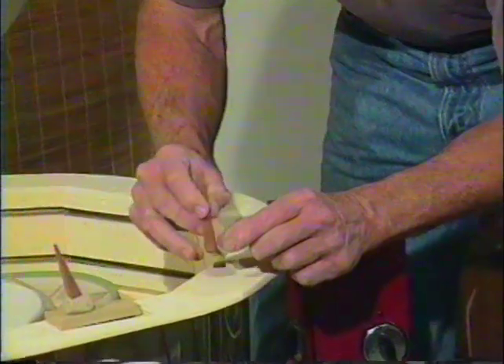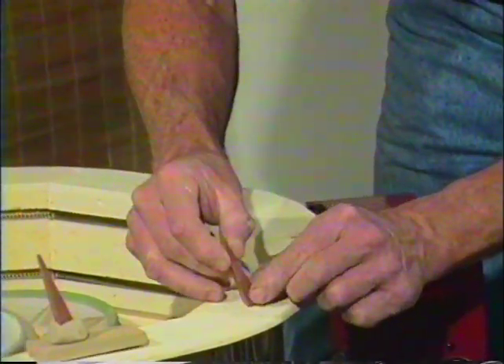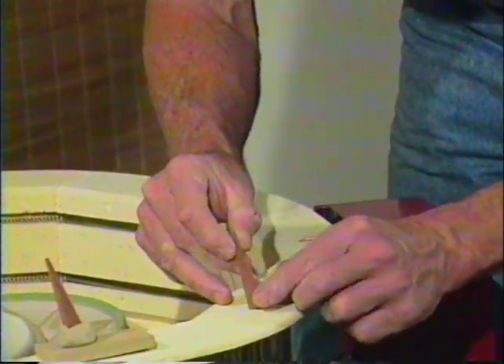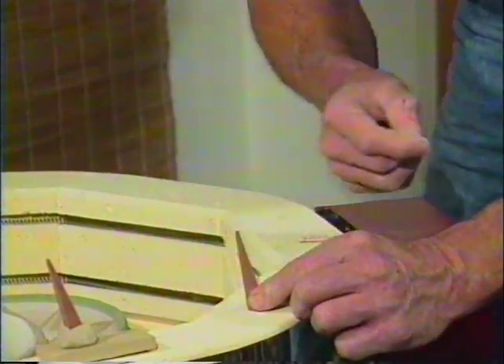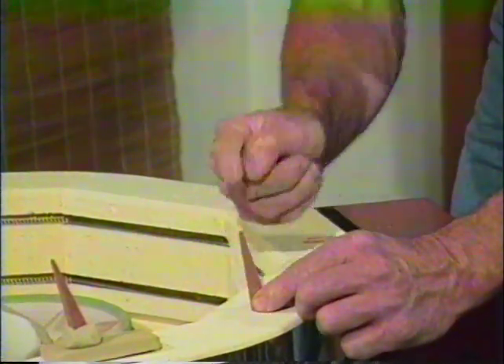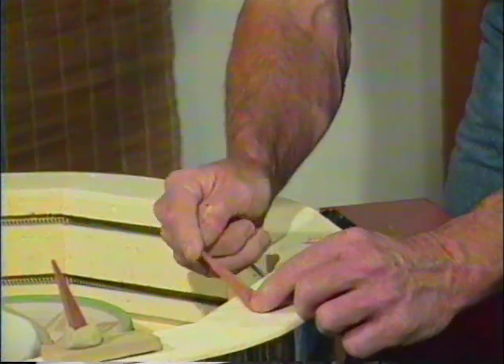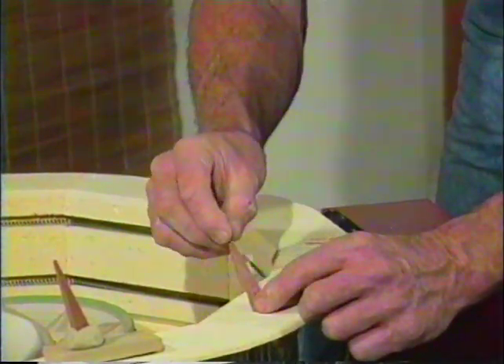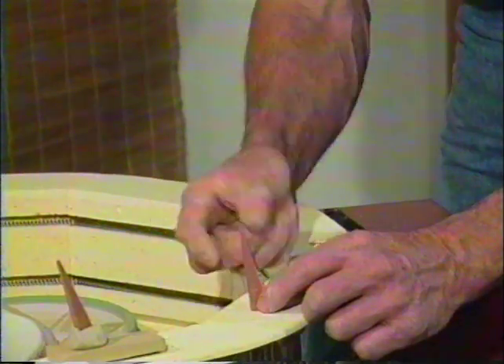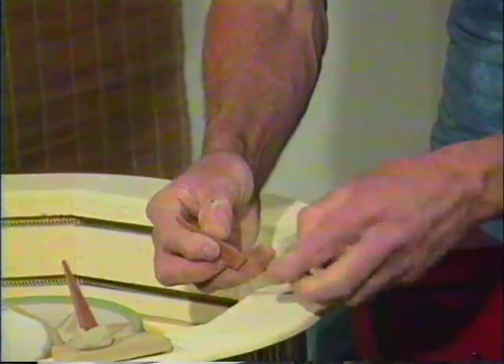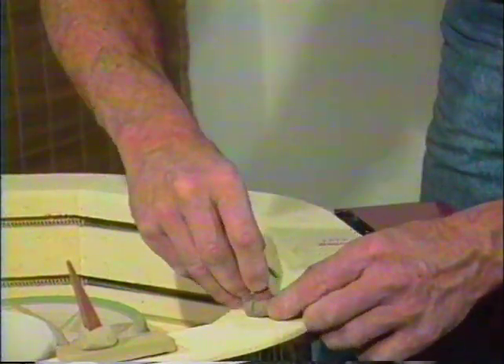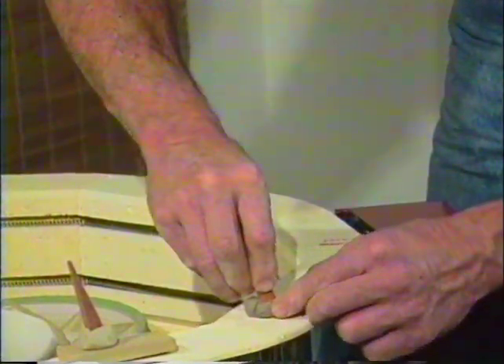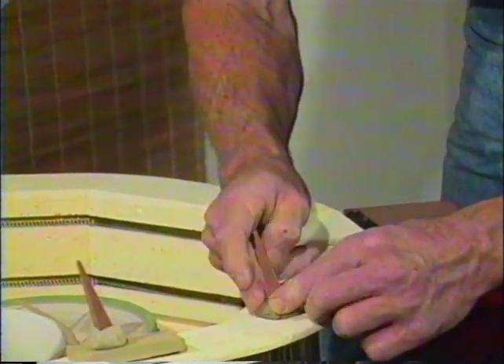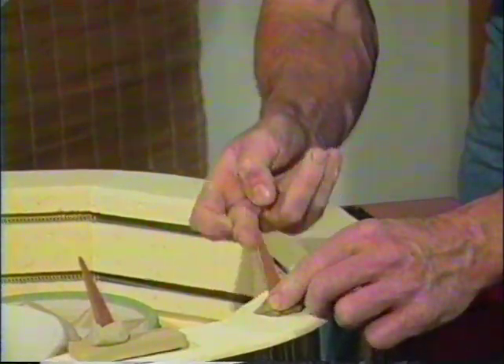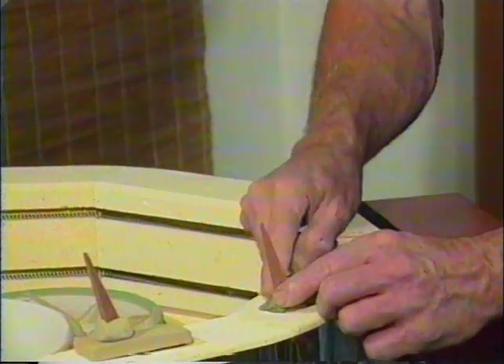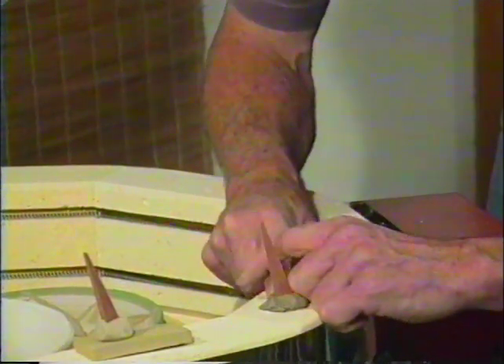But what they'll tell you basically is that the cone's got to be placed so that when it's situated, it's at a slight angle to the direction that it will fall, and the flat side is on the underside so that it can fall across the flat side. So you take a little pad of clay, press the cone, holding it by the base. They're very brittle, so don't hold them by the nose. Hold it by the base, push it in so that you've maintained this angle here, and now when the cone falls, it will fall like that.